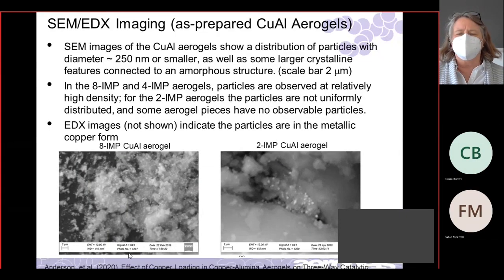Okay, so we took SEM images. These are 2 microns, not as close in. With the 8 and the 4, we would see particles. It's a little hard, but you can see those little dots all throughout. We would see them at a lot of locations. For the 2, we didn't see as many. We saw some, but then nothing here, nothing here. We looked at different locations and we just didn't see as many, which makes sense, because there's less of it.